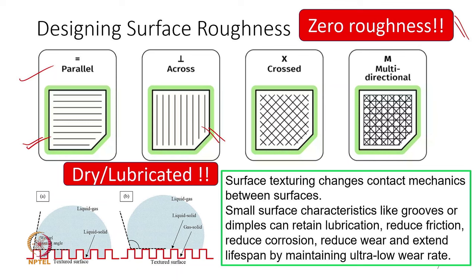Why? The reason being, if the oil is getting squeezed out or leaked out easily, the lubricant is not performing well. When the roughness is in the perpendicular direction, the lubricant, because of the sliding, moves in this direction, and because of the surface roughness, pockets are created and oil remains there, which is like surface texturing. So that is preferable. One more option was the crossed one. This is also okay. This will give the best result, this will give an average result, this will give a wrong result. And multi-directional we may not really require. It may not give sufficient pockets to absorb or keep the debris.